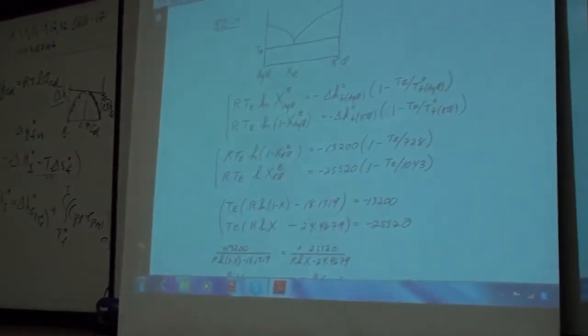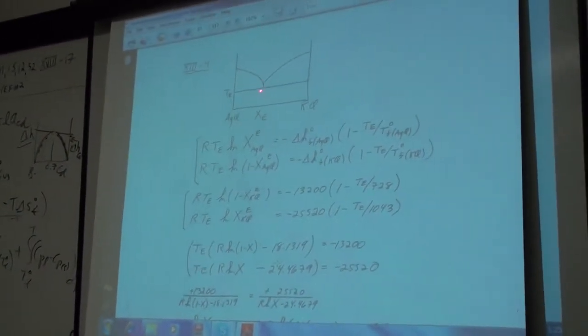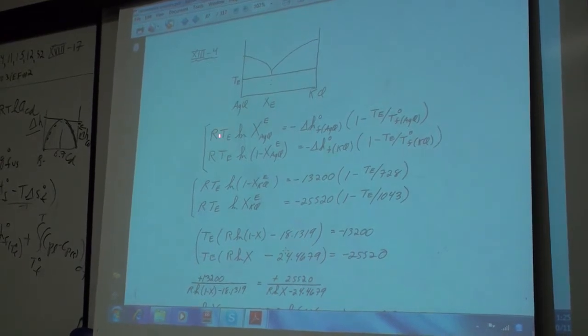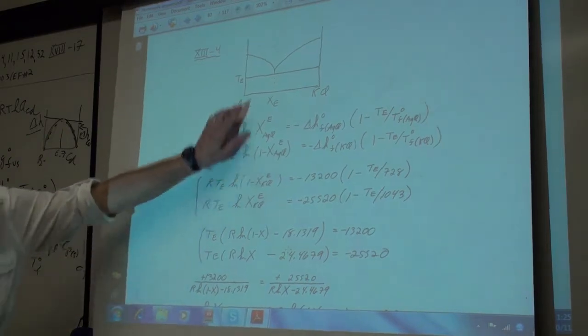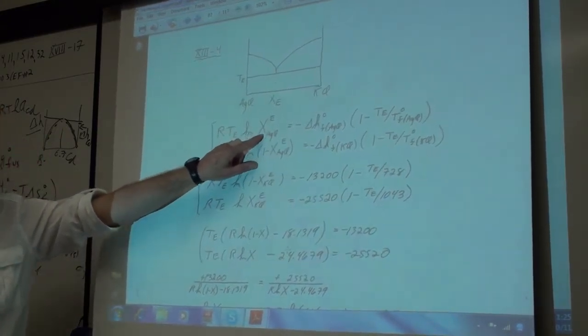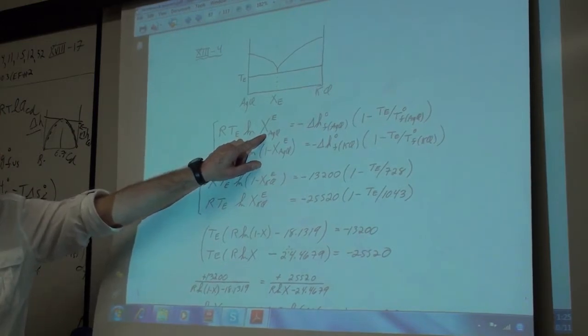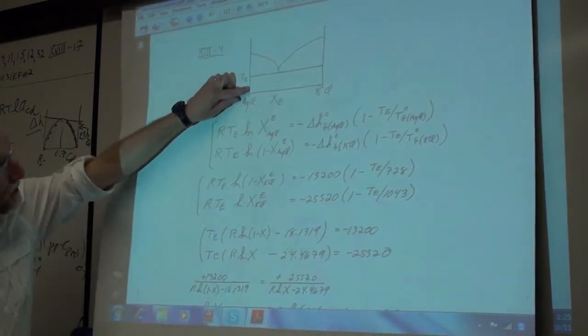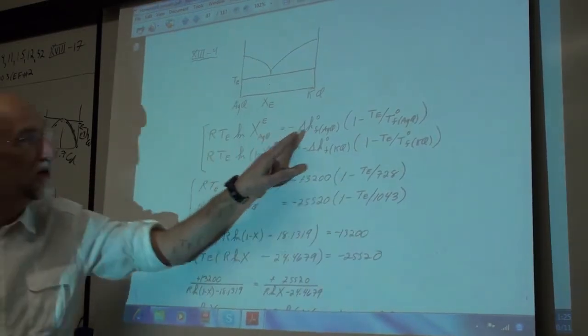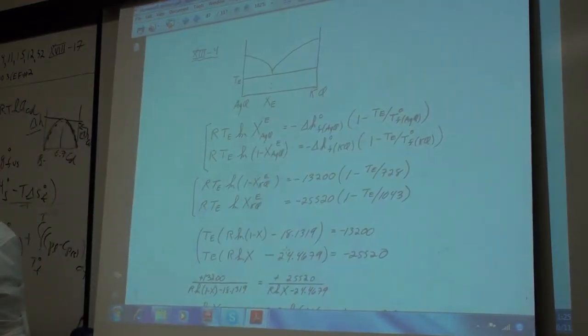So that's what the phase diagram looks like. It's a simple eutectic, no solid solubility. And you have the eutectic composition and temperature, and I'm assuming a liquid that's ideal. So you have the equation basically of this liquidus line. The equation of this line is RT log activity of silver chloride on the liquidus minus RT log activity of silver chloride on the solidus, which comes up to be 0, is equal to this.